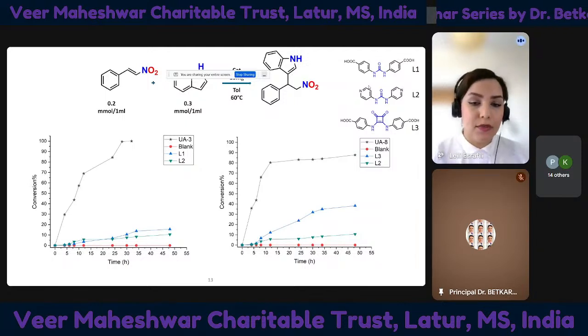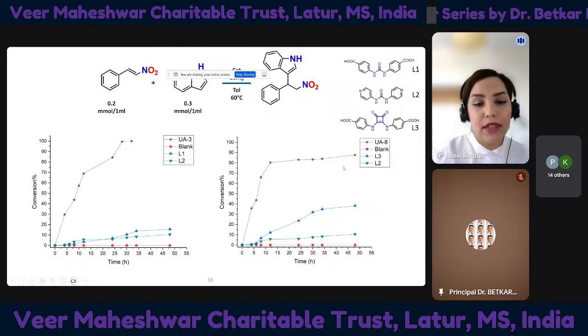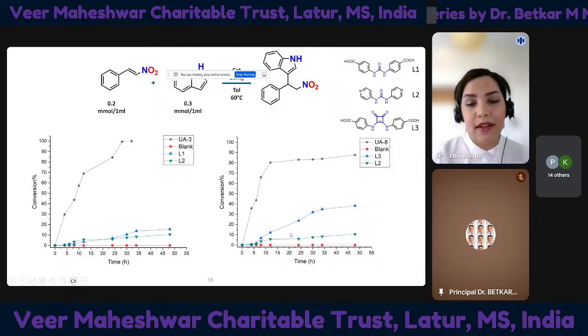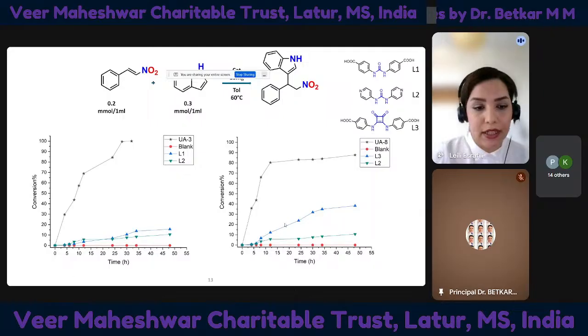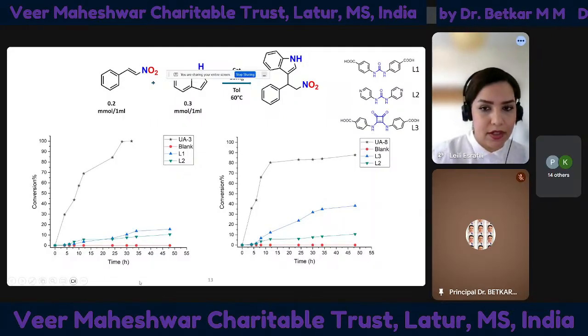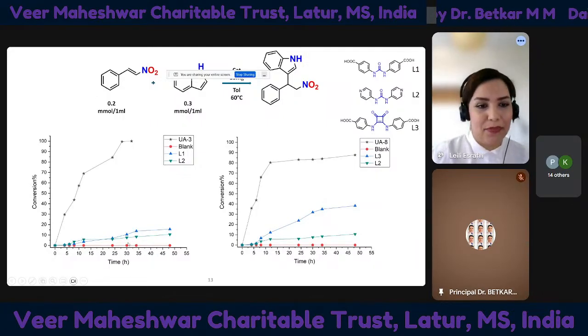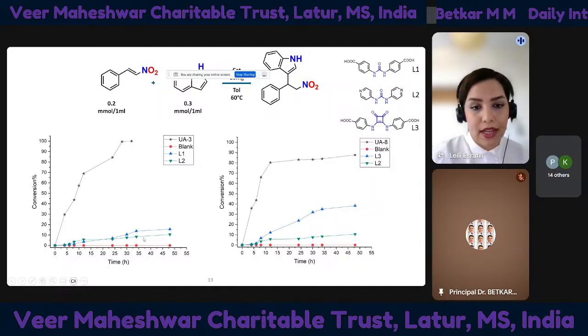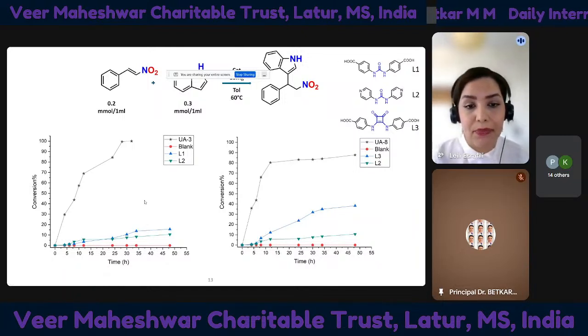We evaluated these MOFs as a catalyst for the Friedel-Crafts reaction compared with the isolated molecular linker. The MOF showed significantly enhanced activity. These are the diagram for MOF, and these are for the isolated linker. As you can see, the catalytic activity improved significantly.